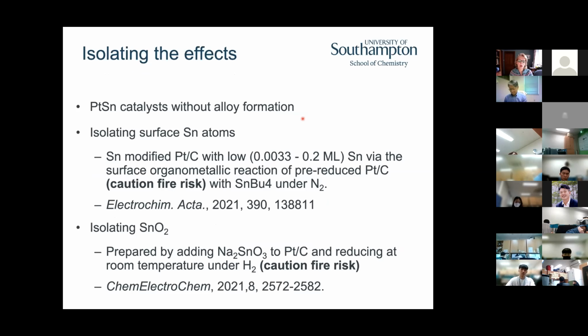So Howard, or Xiaolong Huang, who was my PhD student, had a really good set of ideas. What we're going to do is make some platinum-tin catalysts without alloy formation. We can do that to either isolate the tin atoms or isolate the tin oxide. We isolated the tin atoms by using a surface organometallic reaction to deposit the tin on the platinum, at really low coverages. This catalyst is not meant to be a commercial catalyst. It's a model catalyst that's going to allow us to explore this phenomenon.